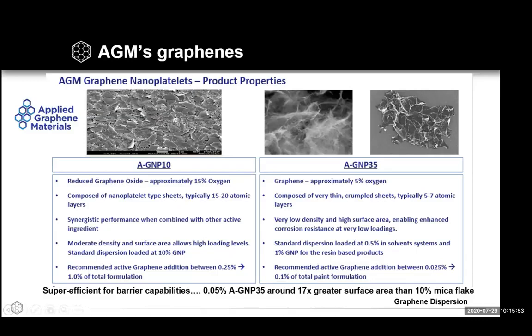And it's a kind of good general purpose material for use in a range of applications, whether that's composite materials or coatings technology. And typical loading levels that we would deploy this material in the end-use application would be at around 1/4 to around 1%. So we have to think through how we will deliver that type of doping into the end-use application. And that's what this presentation is all about.